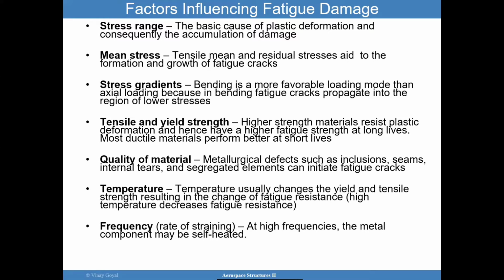So stress range is really the basic cause of plastic deformation, and consequently, it is the one that can cause the accumulation of damage. Another point I want to make is the mean stress. If you have a mean stress that exists in a part, you're also likely to influence fatigue damage. Stress gradients, for example, I'll show you later that bending is a more favorable loading mode than axial loading, because if there's a bending of a part, fatigue cracks will propagate into a region of lower stresses. And so it is proven, and I'll show you some data, that bending is actually more benign than if I were to axially load the sample cyclically.